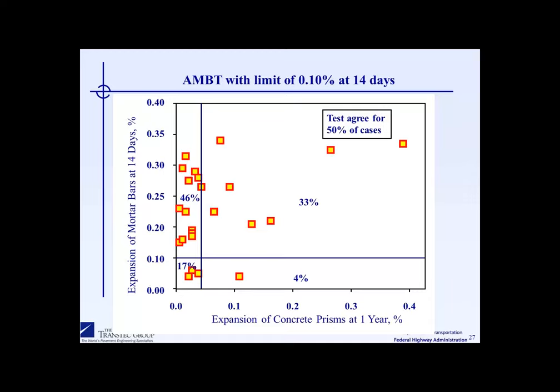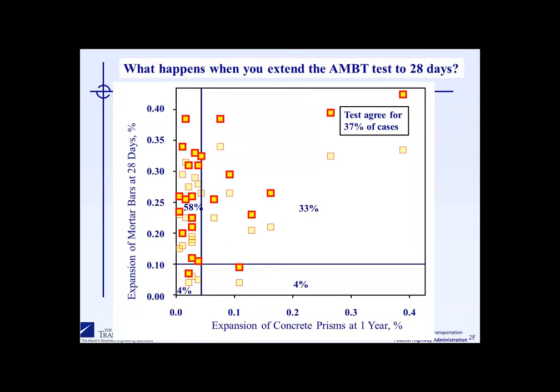What you'll see particularly are a lot of aggregates in this quadrant here, where they fail the mortar bar test, but they actually do quite well in the concrete prism test. This is due to the fact that the test is very aggressive, and the high temperature will make some aggregates expand, whereas they wouldn't expand under normal lower temperature conditions.